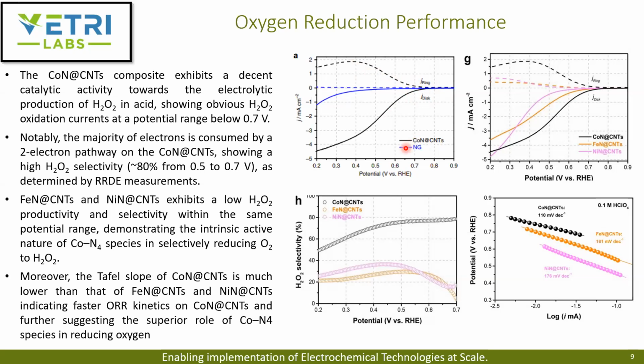And they purchased nitrogen doped graphene to see how that performance looks for peroxide production, and they can see that it doesn't have any peroxide oxidation at all. And as we know, the majority of the electrons are consumed by this two electron pathway, showing a very high selectivity. We can see here it's somewhere between 50% to 80%, and in this region of about 0.5 to 0.7 volt, it's somewhere close to 80% overall.